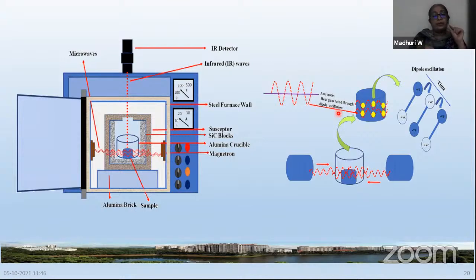At a very short interval of time, of the order of a few minutes, you know, 30 minutes would be enough for a 1 gram pellet to be sintered, if you know the perfect temperature it needs. And further, the other advantage of this is you need to have only a lesser temperature.